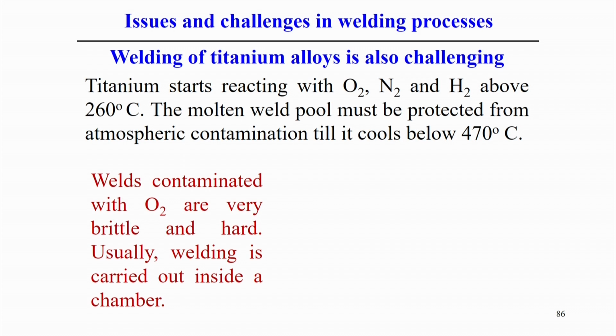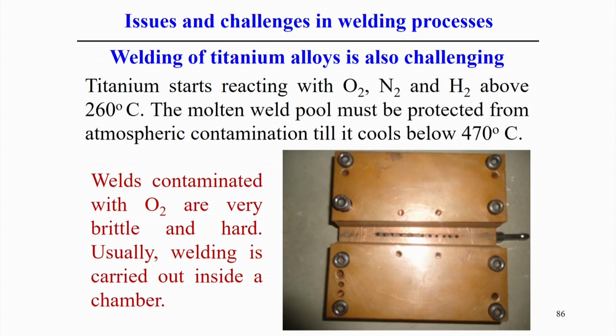It may not be so severe in the welding of steel, but welding of titanium is very difficult, because it easily reacts with oxygen and hydrogen, and the oxygen becomes part of the final weld joint. So welds can be contaminated with oxygen, and that creates a very brittle and hard weld. That's why, to avoid atmospheric contamination, in most cases we do the welding of titanium alloy inside a chamber, or some modification can be made so that this oxidation problem can at least be reduced.